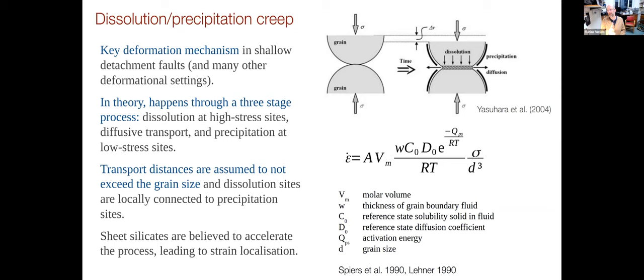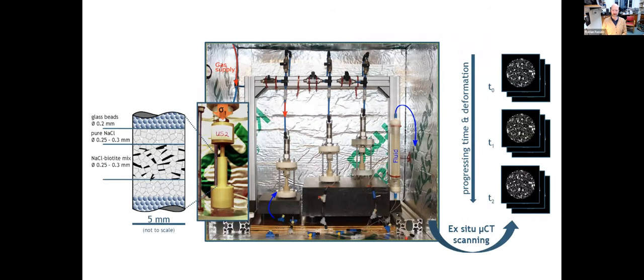So essentially the task at the onset of Barrett's PhD thesis was, let's make a stylolite in the lab and watch it. The reason we wanted to do that is because we were really interested in the porosity evolution in the process. Barrett also set up her own experiments, and these are now offline, meaning they are not done on a CT scanner, but they are scanned. She also designed her own samples here. Pretty cool. These are little oedometric cells made from a high performance polymer that we use a lot, PEEK. The samples here are 5 millimeter diameter.